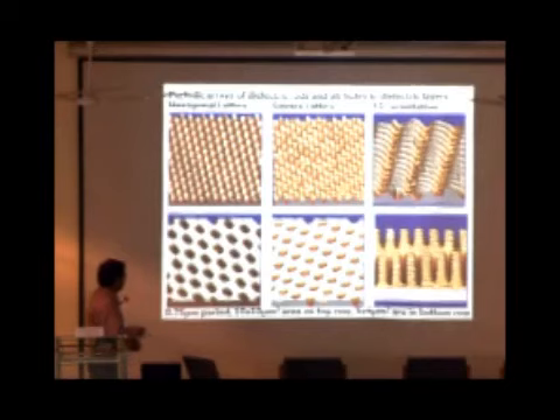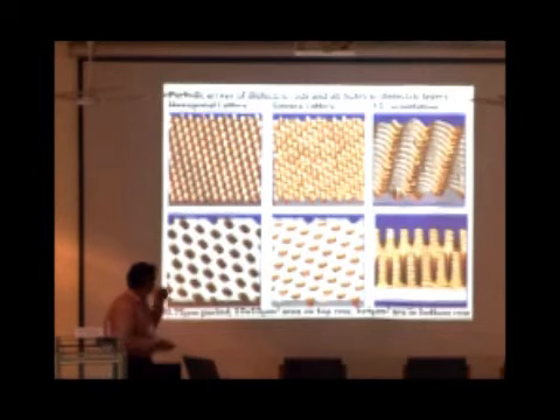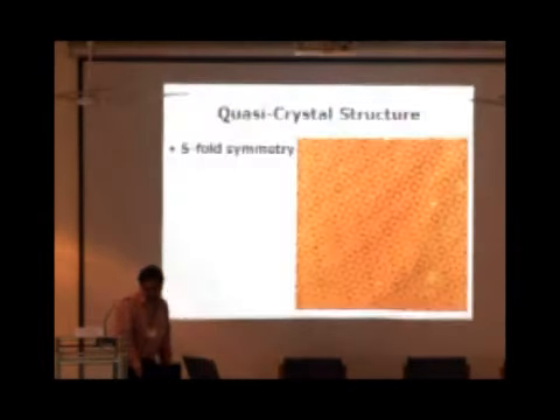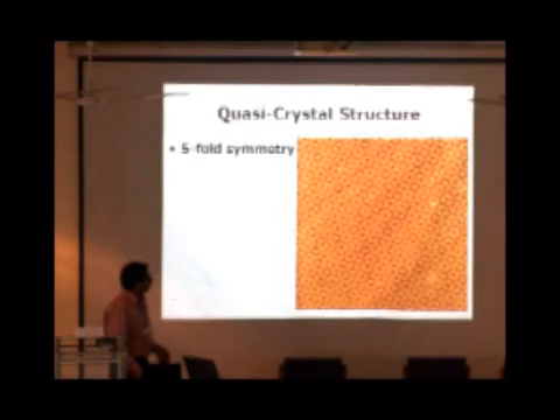So these are all submicron features. You can go as low as 0.4 micron. The smallest feature we could get was about 50 nanometers using interference lithography. We made this quasi-crystal kind of pattern in dielectric.